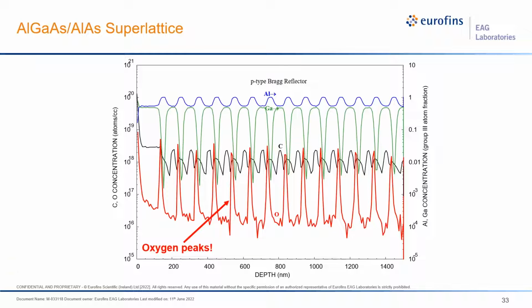Another strength of PCOR SIMS is its ability to profile unwanted contamination species. The most ubiquitous of these is oxygen, which can produce contamination spikes at the growth transition between the high and low index layers of the p-DBR. Knowing the exact location of the oxygen spike in the growth sequence is often helpful in trying to isolate and eliminate the source of contamination.